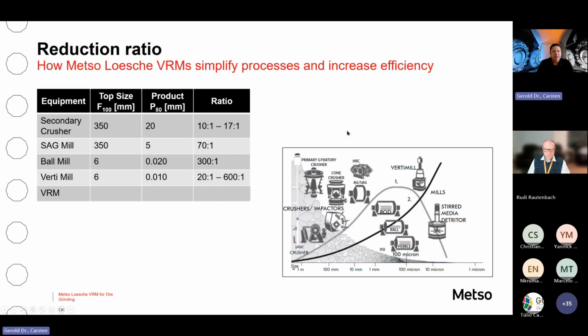The reduction ratio of these machines is really astonishing, and therefore processes can be much simpler with increased efficiency in comparison to other technologies. You all know the ratios mentioned above, but in the Loesche mill, you can feed 150 millimeter and grind it down to 20 micron, which is actually about 7,000, but we didn't want to go that high in the numbers. Taking the picture on the right-hand side, you see all the different comminution equipment for the given particle sizes.